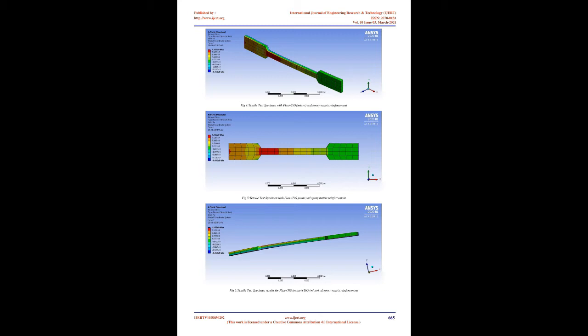Fiber composites comprise fiber and matrix phases, and the mechanical behavior of the composites is highly dictated by the fiber and matrix properties. Microstructures, for example, fiber shape, fiber cluster, and volume fraction of fibers are also more significant in determining the mechanical properties. Micromechanical models have been utilized to anticipate the properties starting from the inherent properties of their constituents, and these models show that the fiber strength isn't always fully utilized because of poor fiber matrix interfacial adhesion and fiber length.